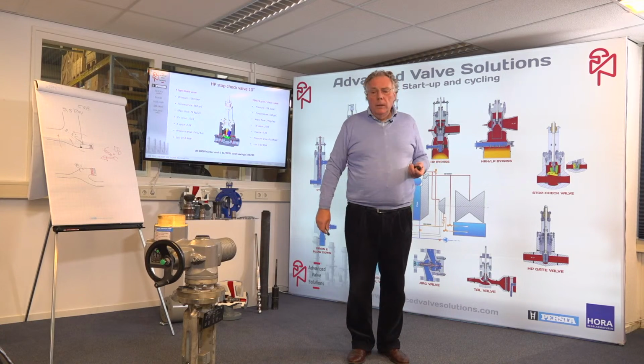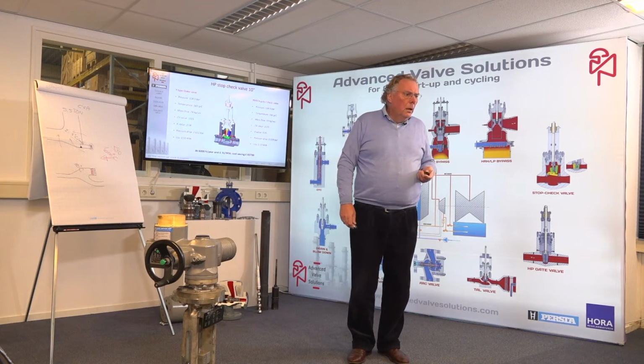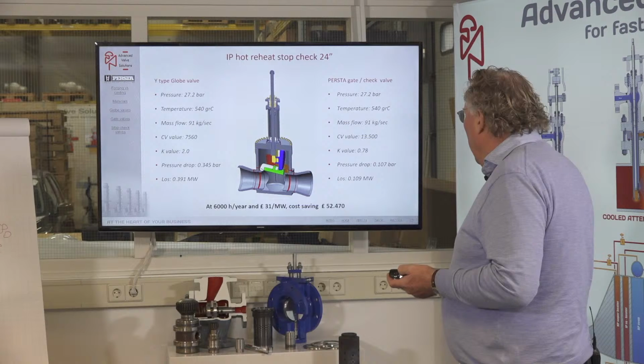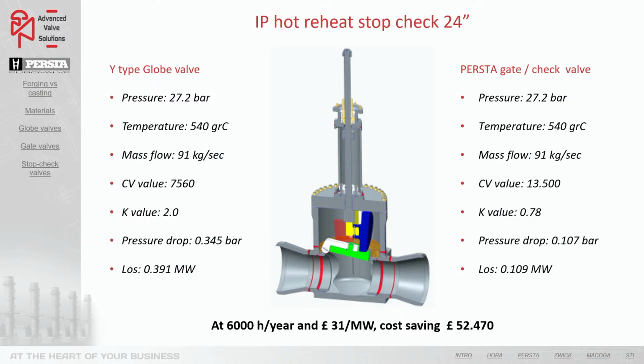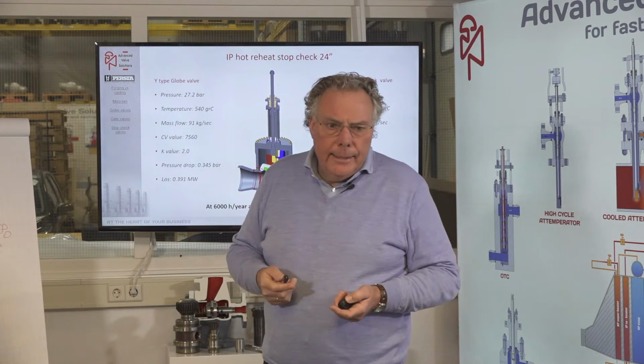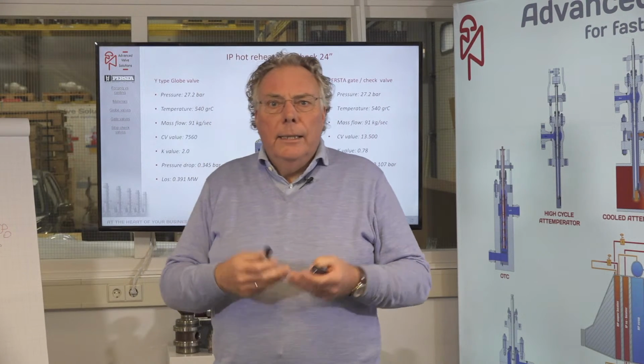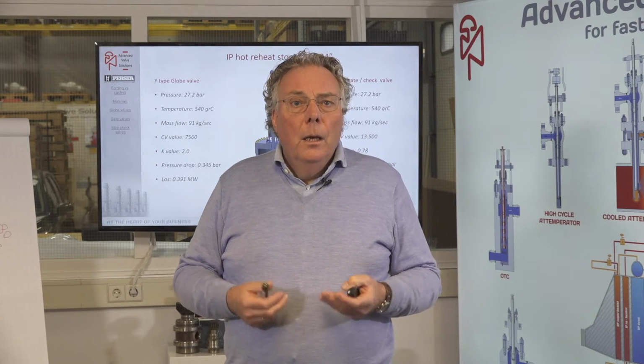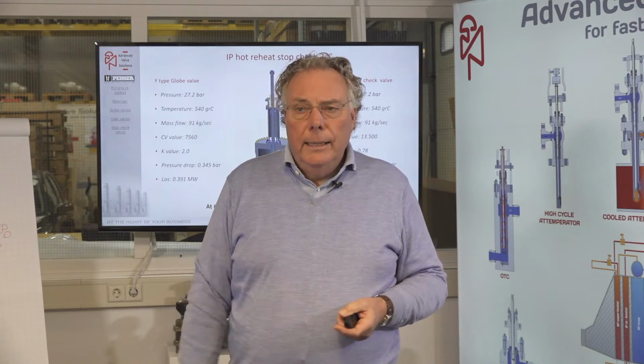And that is really cash money. Another calculation we made is we have, in this case, a 24-inch hot reheat. Pressure drop is again 0.35 bar versus 0.1 bar. So it's also a quarter of a bar less loss. Good valves available if you like it.